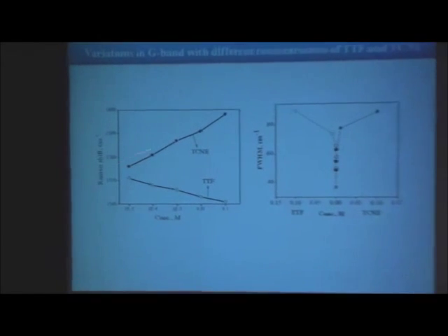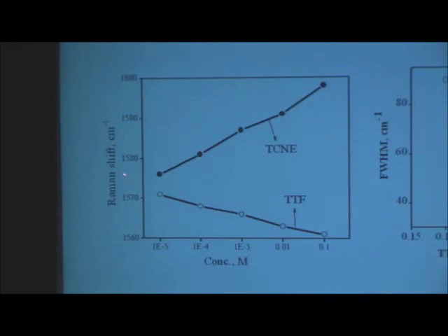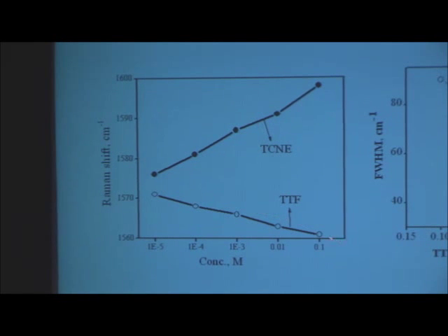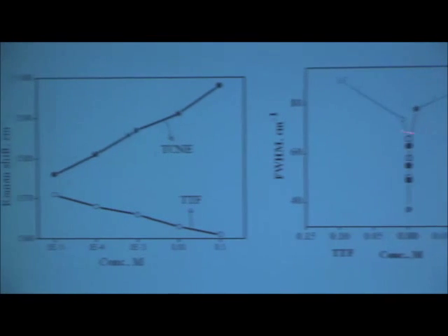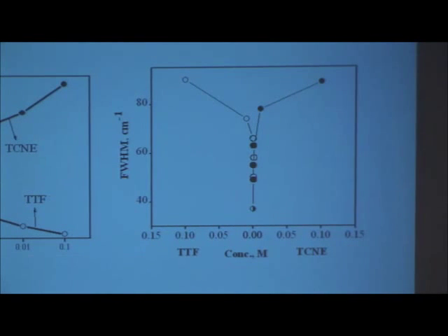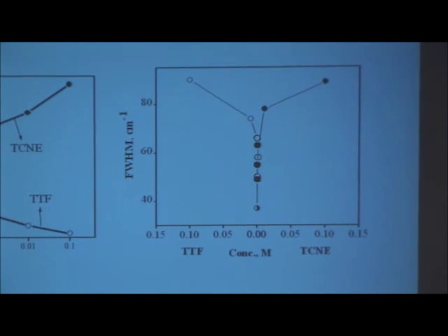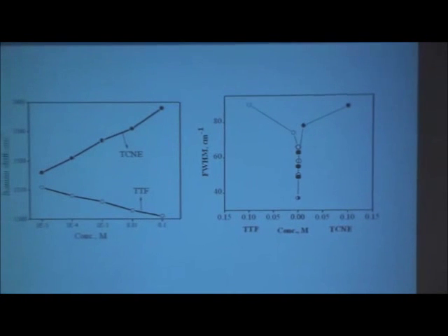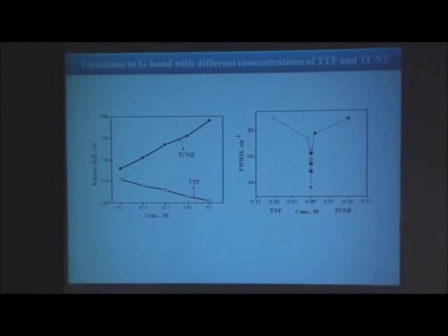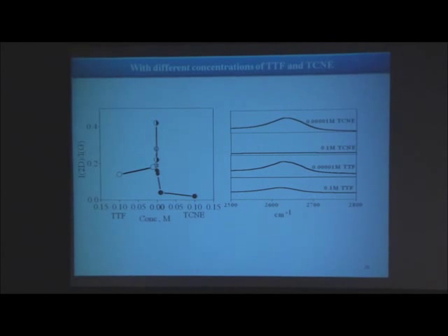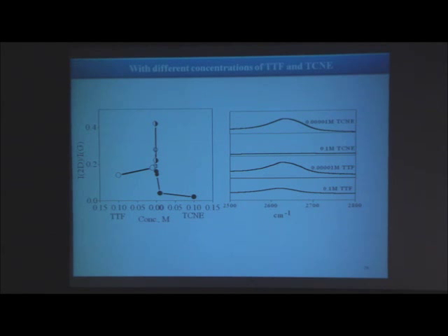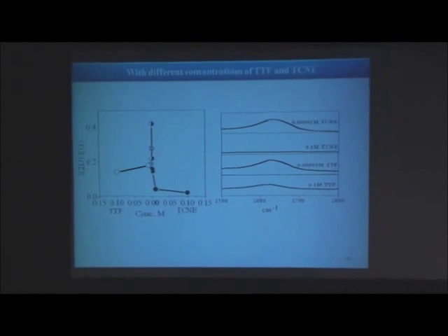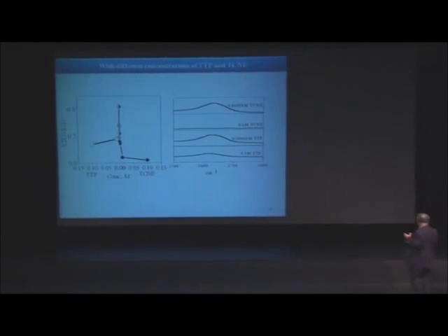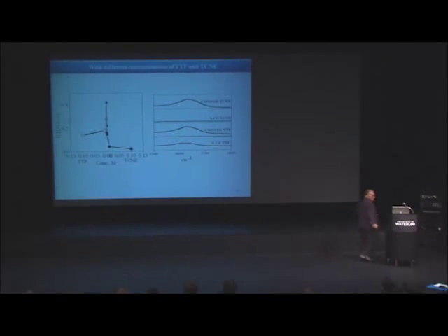TCNE increases this G band enormously. Tetrathiafulvalene, the donor molecule, decreases this. And the width of the bands, of course, is very sensitive. The width of the band also shows very marked changes on donor-acceptor interaction with graphene. And the same is true of the 2D band. You remember the 2D band, which is characteristic of single-layer graphene. The sensitivity is unbelievable.